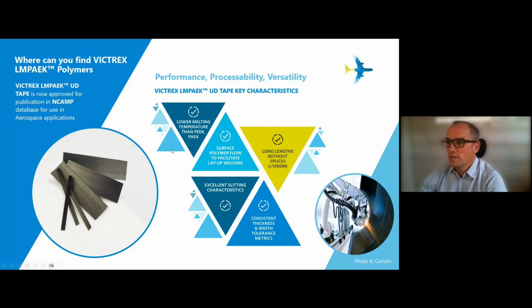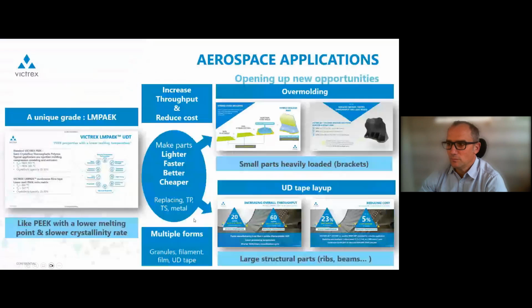Due to the lower melting point than PEEK, the resin flows well during the layup process. Also, in terms of length without splice, the tape has excellent characteristics, and overall the quality of the tape in terms of thickness and width tolerance is also pretty high. We could spend the rest of the day on that slide, but just to give the message from a high-level standpoint, that's what we call the value proposition of the LMPAEK UD tape, which has been quite adopted today in the aerospace world.